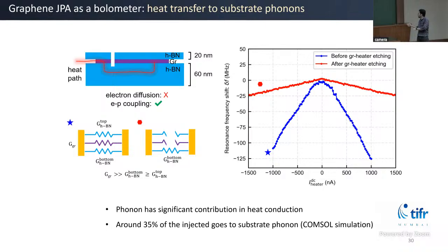We also did a COMSOL simulation to model this, and there we found that 35% of the injected heat actually goes to the substrate, and your junction only sees the rest of the heat.